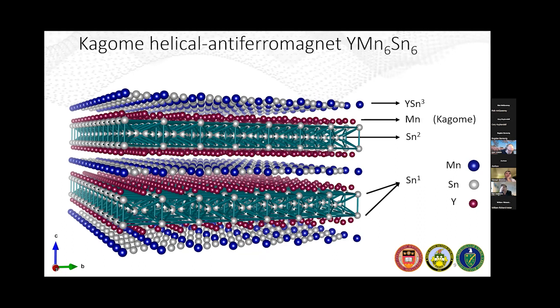So I might as well mention at this point that out of maybe 30 or 40 samples that we actually attempted to cleave, maybe only 5 or 6 successfully cleaved to reveal a flat plane for STM measurements. So the way our experiments work, we get these from our collaborators. So this was from Hechang Lei. And then we put them in vacuum. We rip them apart in vacuum to expose a clean surface and put them directly in the STM. So these crystals cleave somewhere between these two.